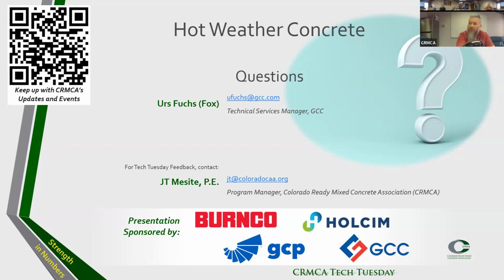It sounds like we've got a question here in the room as well, though. Yes, of course. Everything you presented shows that you lower the temperature at, let's say, 70 degrees F. But how do you keep that? Because it seems to imply that the temperature can be kept quite long at a low temperature. You mean the ambient temperature? Yeah, you do all these things to lower the temperature, and then you have a graph showing that at the lower temperature, the strength will keep improving. But this temperature cannot be kept low all the time. No, it cannot. Well, the target is the time of placement. So just the placement is enough? Yes, that's the target, to get it lower at the time of placement. And then it's going to accelerate regardless.